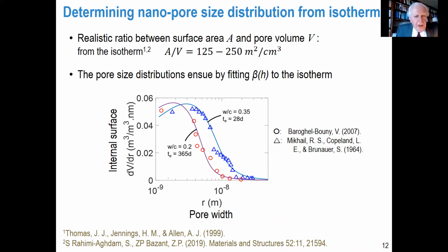An interesting point is that we get a somewhat different estimate of the internal surface area. The adsorption typically gives a surface area of pores of about 500 square meters per cubic centimeter of the material. It actually implies that the average width of pores is about half a nanometer. Now, with this calculation, we get about 125 to 250, which implies an average width of pores of 1 nanometer, which is about 4 water molecule thickness.